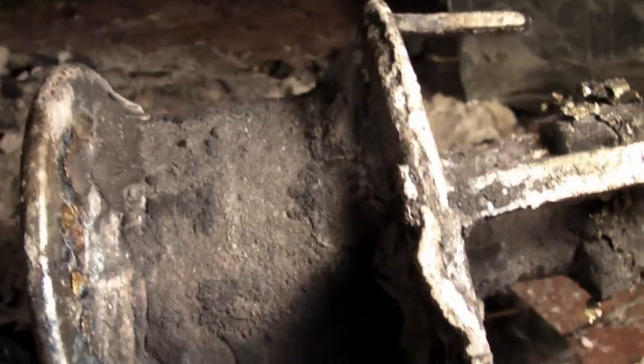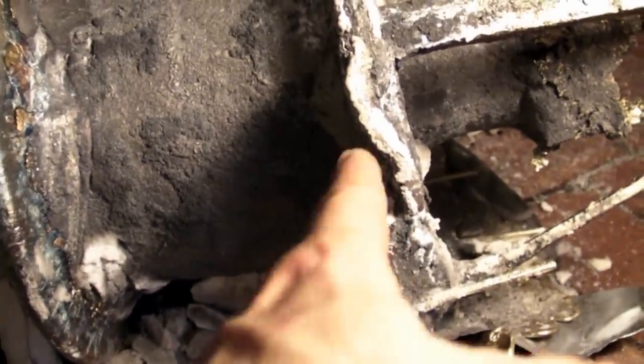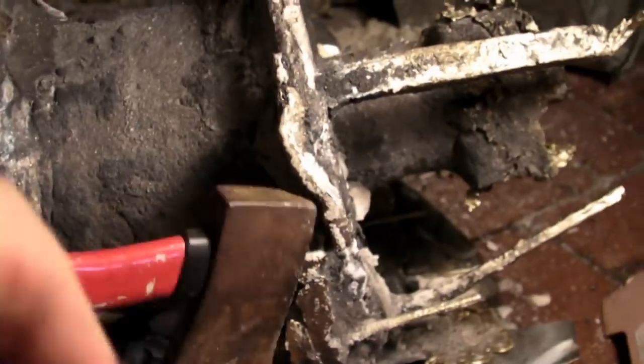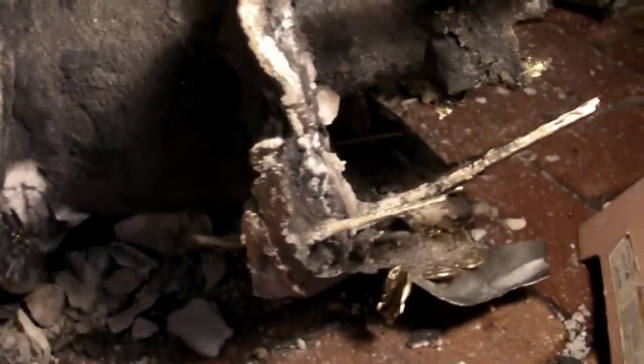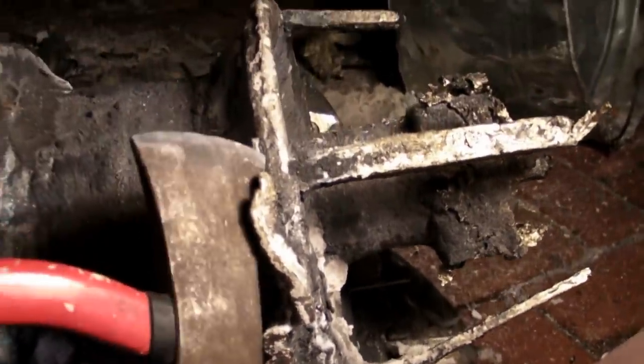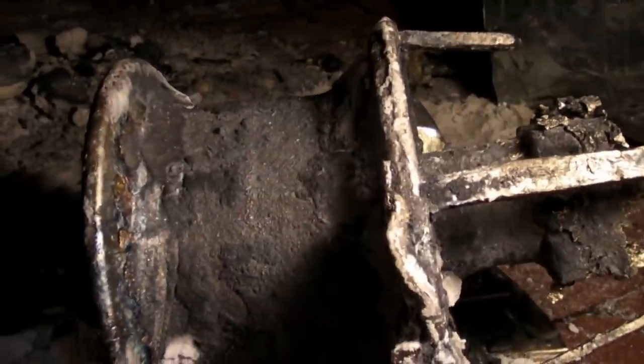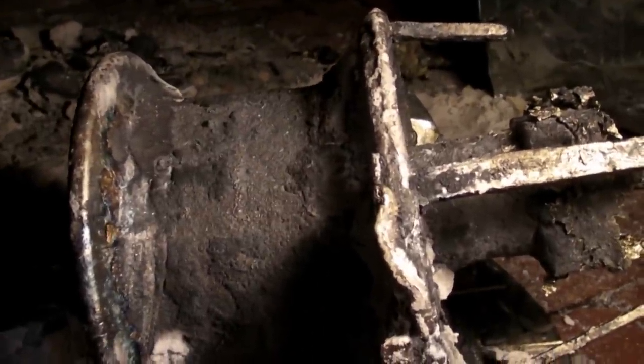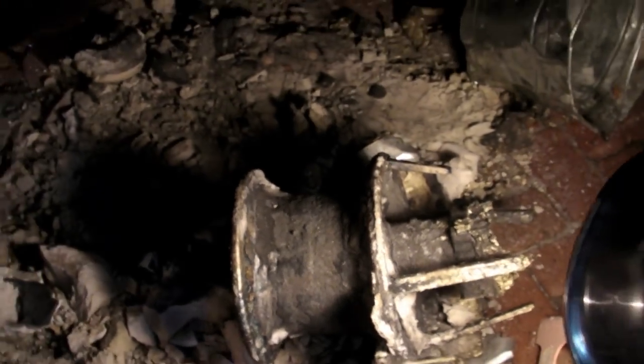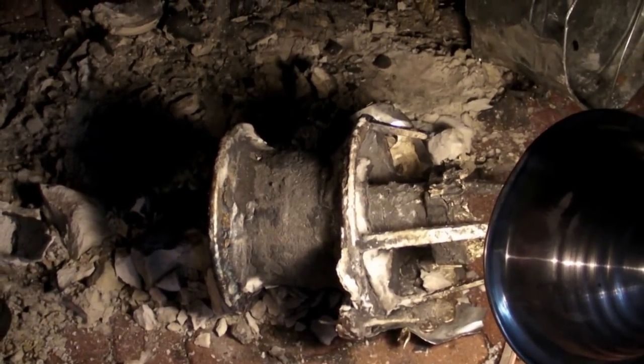Well, on further examination, it's an abortion. Because what happened is the mold broke underneath that flange and the whole side pushed upward, and then the metal shot out on the side here. What's really bad is now it's a huge hunk of metal that we can't get into a crucible. We have to cut it up in a saw. We've got to figure out a way of cutting the damn thing up with a plasma. That sucks.